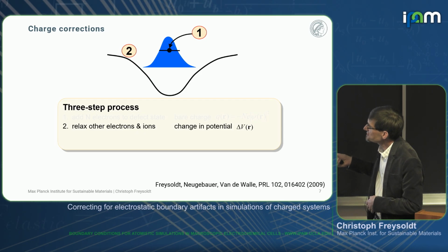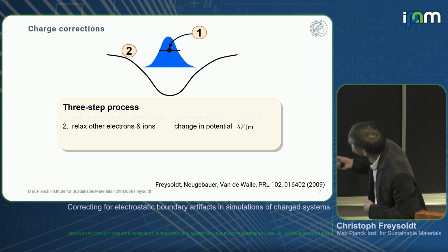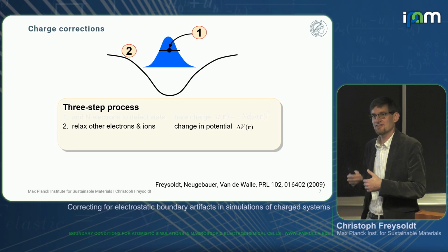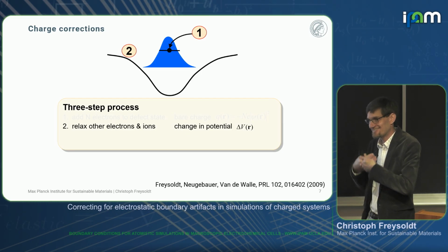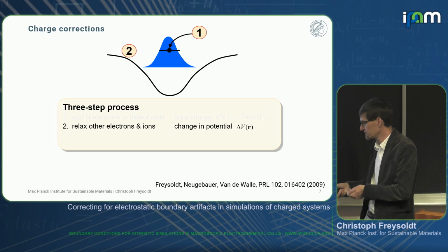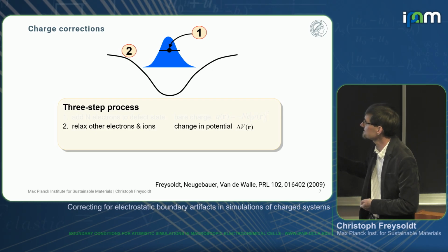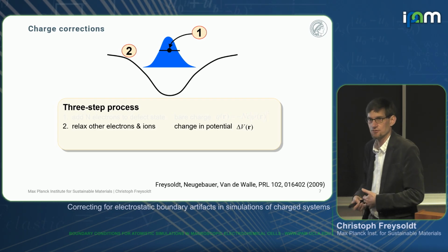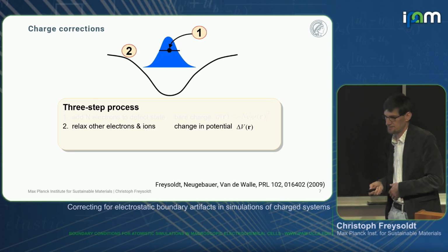When we have this change in the electrostatic potential, which now contains all the screening effects, and combine that with the bare charge density, then we can compute an electrostatic energy which has exactly the energetics of the DFT, because all the screening effects are contained in the change in potential, but we don't include the screening effects additionally in the charge, which would have a double counting effect.